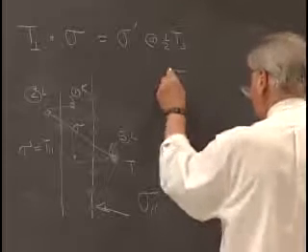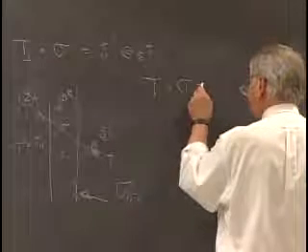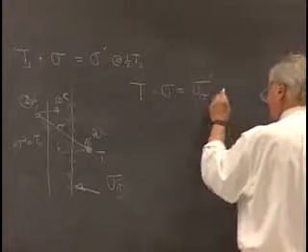And this gave us a new theorem that a general translation that had a part t perpendicular and a component t parallel, when it followed a reflection operation, was equal to a net effect of reproducing the object by a glide plane sigma tau prime. It had tau equal to the part of the translation that was parallel to the reflection part of the locus, and it was located always at 1/2 the perpendicular part of the translation.